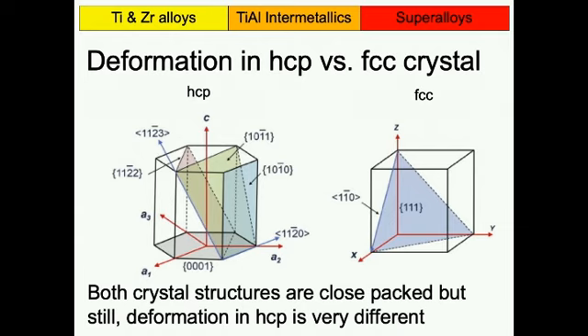So here I've drawn the HCP crystal and the FCC crystal. And both crystals are actually close packed. But deformation in HCP is fundamentally different from deformation in FCC, in the way that in HCP you have a number of slip planes. You don't just have one type. You have this one here, the 10-10, so the prismatic plane is a slip plane. And so what makes a slip plane actually? Close pack. Yeah, so close pack.